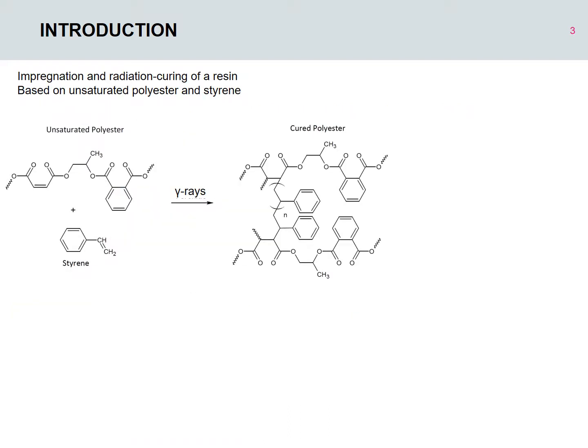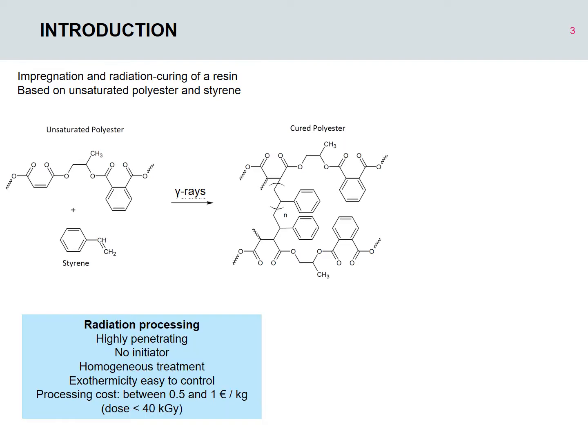Some thermosets, like unsaturated polyester, can be cured by radiation processing, like gamma rays, for example. Radiation processing is interesting because it is highly penetrating. It does not need initiator. The treatment is quite homogeneous. The processing cost is between 0.5 and 1 euro per kilogram for moderate dose, lower than 40 kilograys.